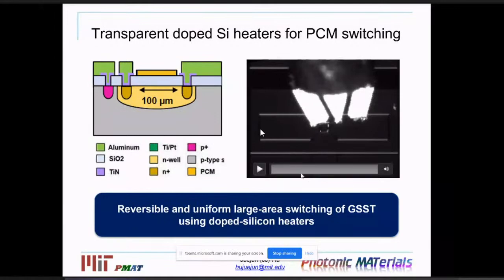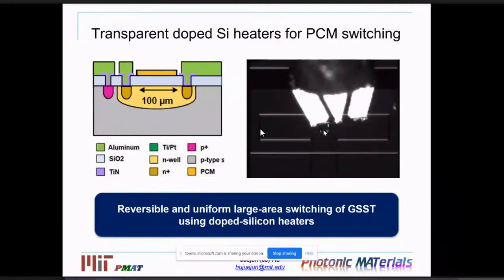That's one way. The other method, which is actually more convenient, is to use the doped silicon platform. Because we can switch this material in situ on the doped silicon, we can do something like EBSD or SAED, selective area electron diffraction, on the material suspended on a silicon heater to verify the structural transition in situ. That's probably the best way to do the switching if we want in situ characterization of the crystalline structure. Thank you. That's why I think these doped silicon heaters are very useful, not only from a photonic device perspective, but also for material characterization.